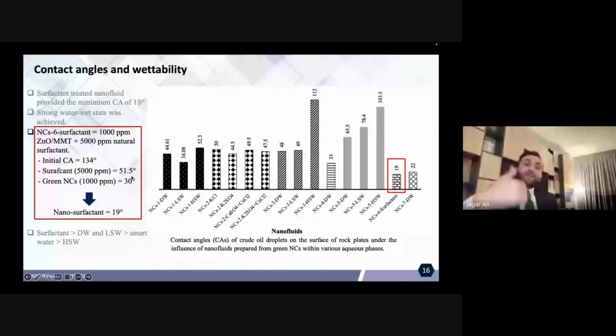When the nanofluid without surfactant, with water, was injected, it reduced to 30 degrees. But when we mixed the nanoparticles with the surfactant, what happened? It was reduced to 19 degrees. That means the nanocomposite that we use is increasing the efficiency and performance of the surfactant as a conventional chemical EOR method.